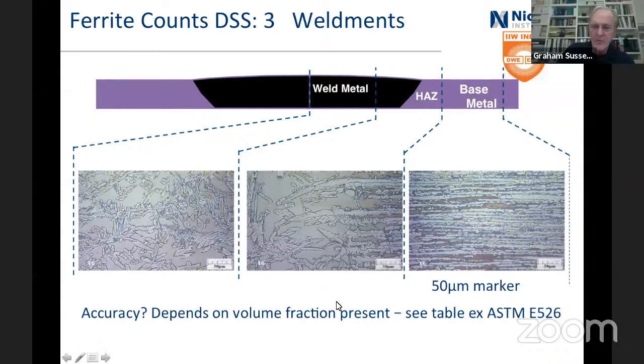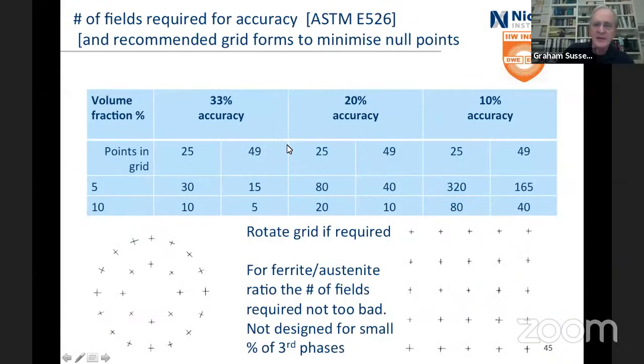Okay, so there are tables. This is out of the standard, and I've picked out a few just to indicate how labour intensive it is. If you're aiming for 10% accuracy on a 5% volume fraction and you're using 25 grid points, you have to do 320 fields. I defy you to do that without going absolutely bananas. It's bad enough when you've got to do 15 and 5 or 40 or 10, but that's the statistics. All this is out of that.